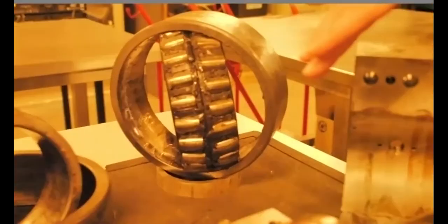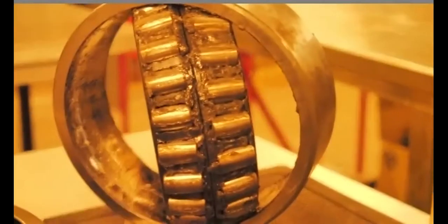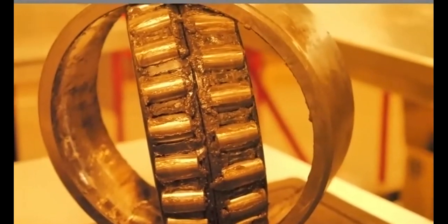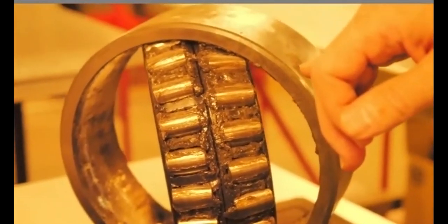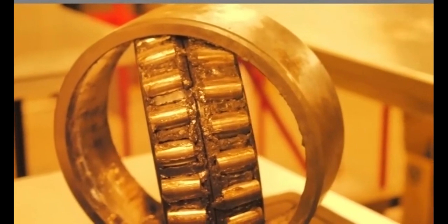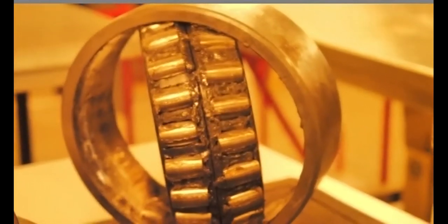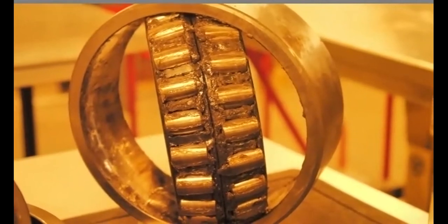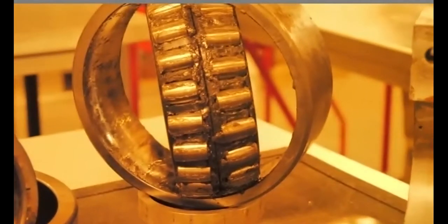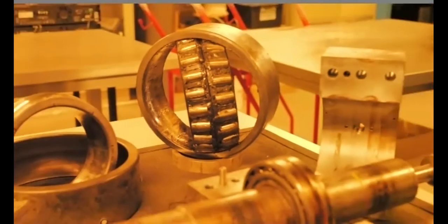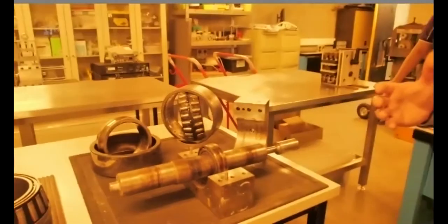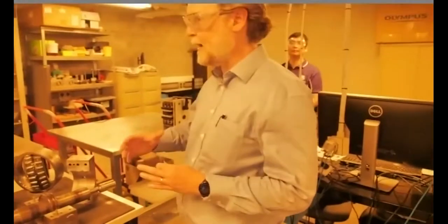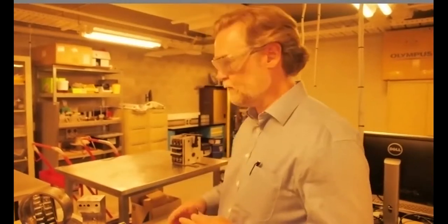And if we look closely into that grease, we've found the main reason for degradation is wear from the rolling contact process. So we've, again, developed a good understanding of the physics behind what's going on and developed models to predict the wear under different conditions, and then tried to optimize that process so that we can maintain based on the actual degradation of the grease rather than going purely by an 8 year schedule. And of course, this saves a lot of money.